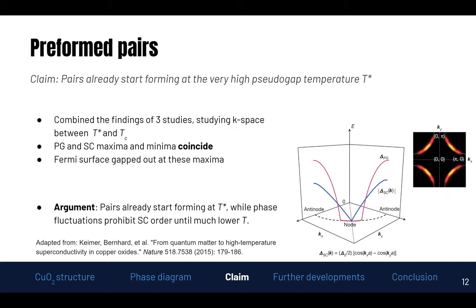What does 'phase fluctuations prohibiting superconducting order' mean? Basically, in a cuprate system that's fairly large, we can have certain Cooper pairs already formed in one region but out of phase with Cooper pairs in another region. In BCS theory, when we get the condensate of Cooper pairs, we need not only the Cooper pairs but also all of them to be in phase. So perhaps it's fluctuations in the phase that prohibit the superconducting state and lead to a pseudo-gap.